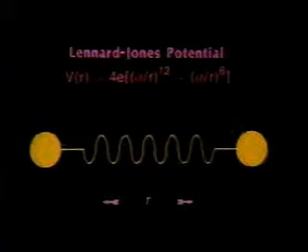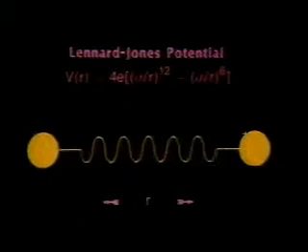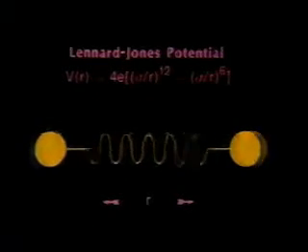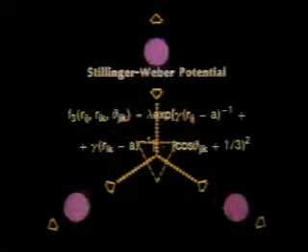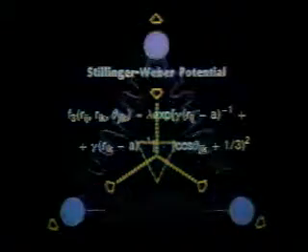Metals are simulated using spherically symmetrical potentials, two-body interactions according to Lennard-Jones potentials. Semiconductors require the use of more complicated potentials, which include three-body interactions. Using a supercomputer, Newton's equation of motion is solved at every instant of time. Nature, of course, solves these equations without our help or that of a computer.